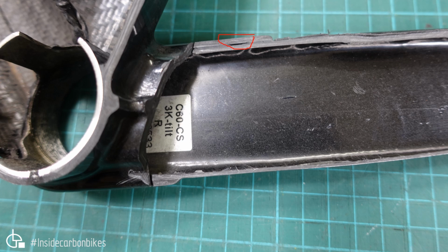You can see the sticker, the C60 CS, which would be chainstay, 3K tilt R, which would be the right hand side. I'd say the 3K would be the external, because the internal's UD. There is a lug, in the lug joint. There's a molding, like a rib through that section as well, to provide some increased support between the chainstays. So that's a stiffening feature.